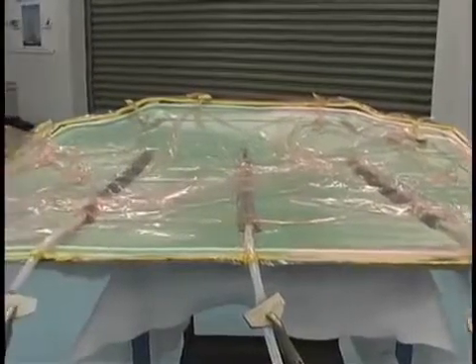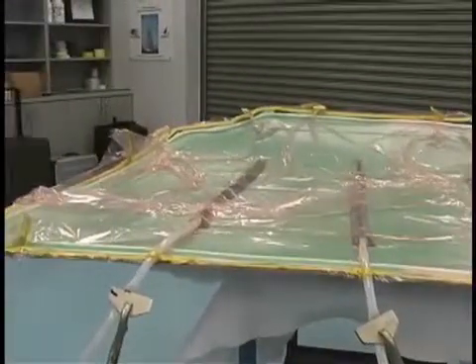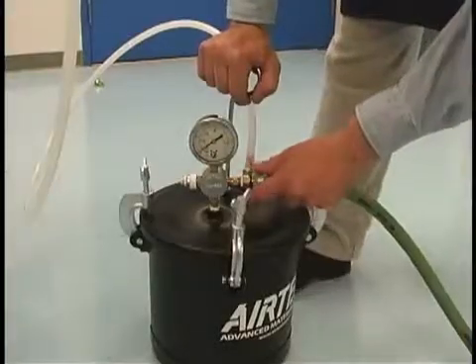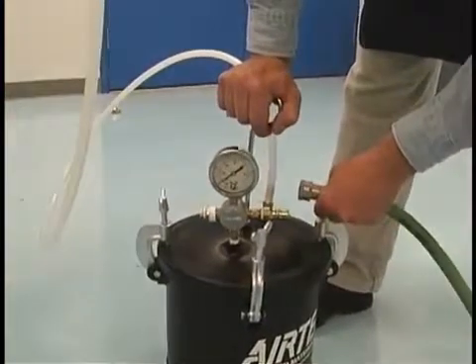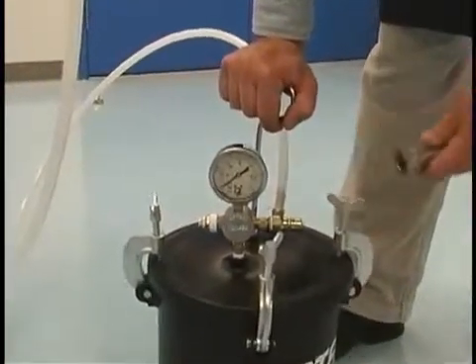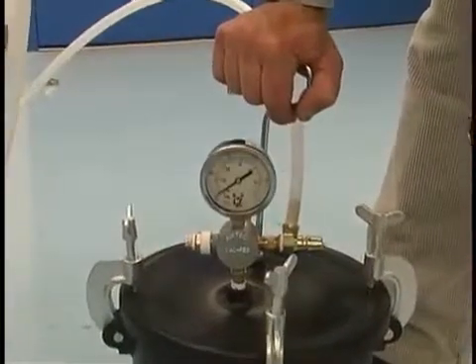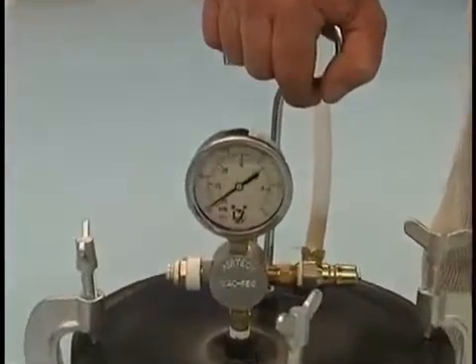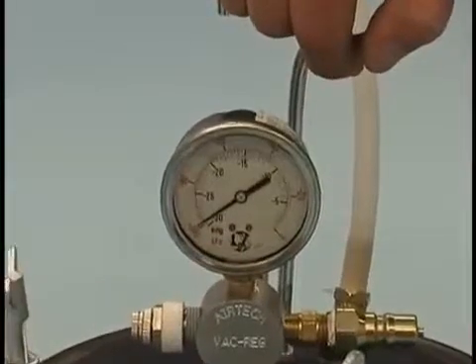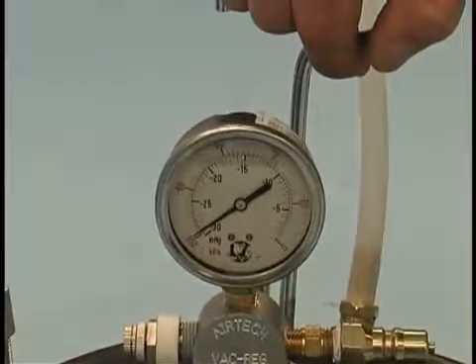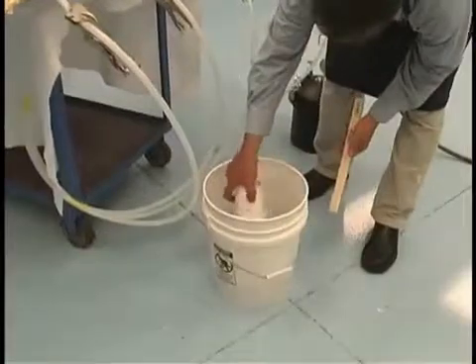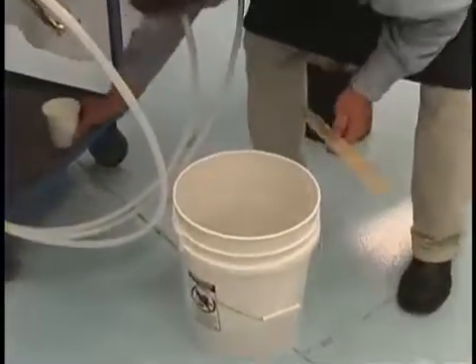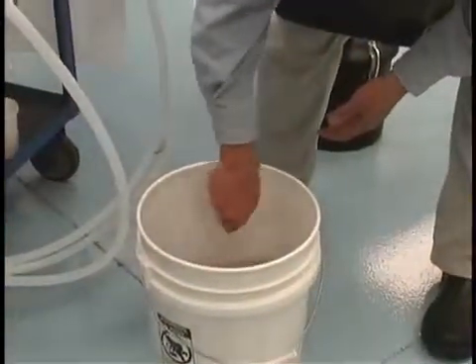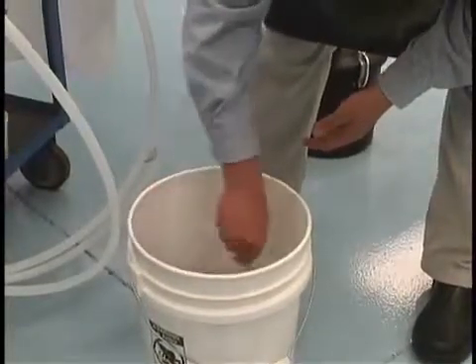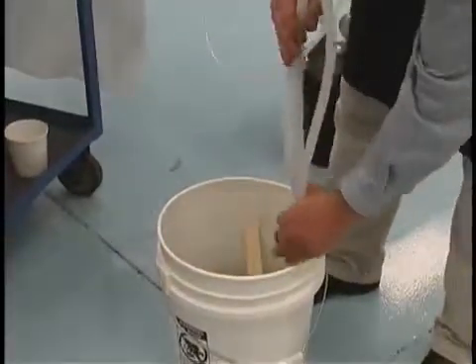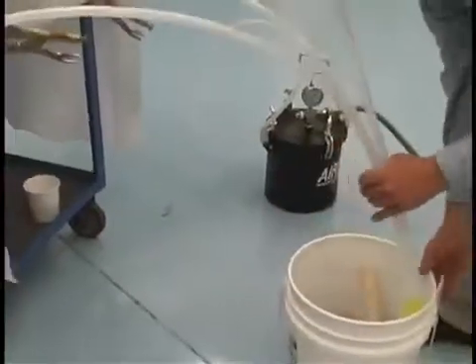Here, full vacuum has been applied, but let's make sure by doing a leak check. We remove the vacuum source and find that over a period of time, there is no vacuum loss. Vacuum integrity is critical to this process. When we are ready to infuse, we first add catalyst to our resin. The inlet tubes are placed into the bucket and the first clamp is released.